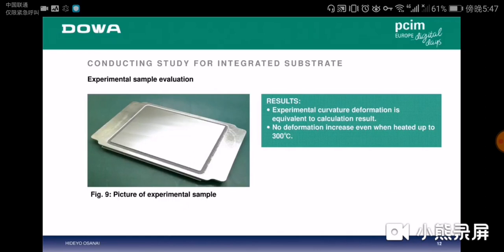This sheet shows an experimental sample of the two-ceramics model. When heated up to 300 degrees Celsius, no warpage occurred. This result confirmed the calculation results.